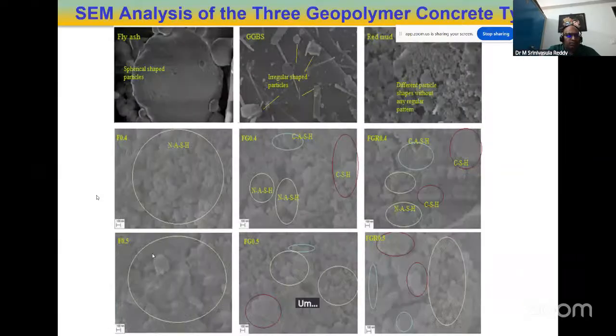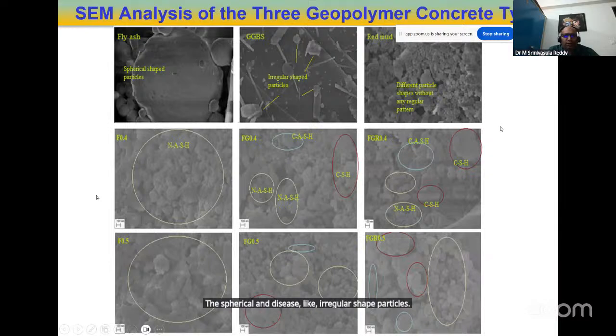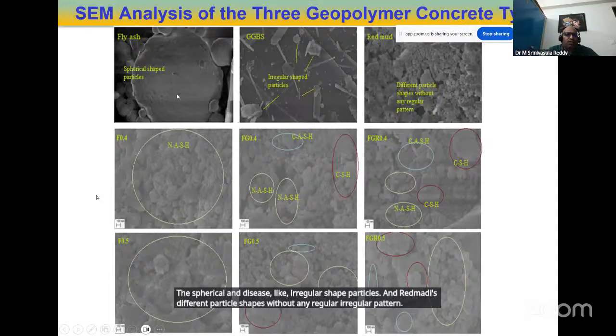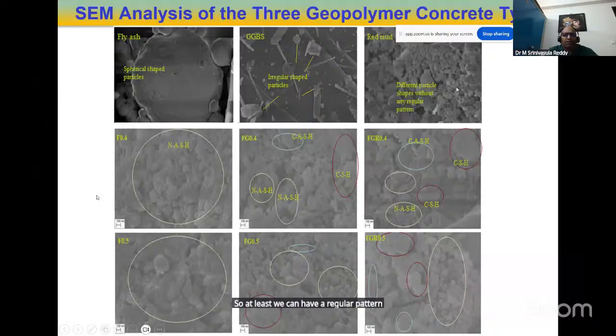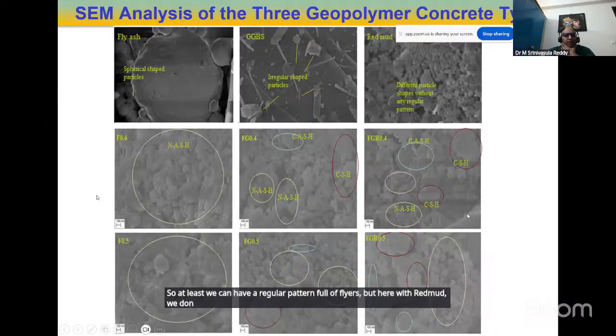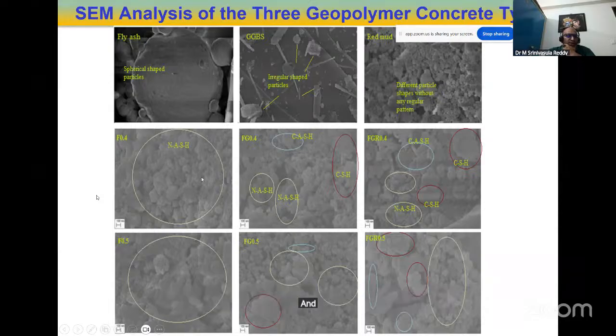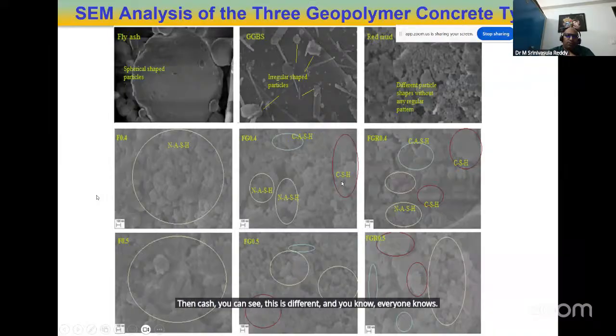And this is the material, the spherical, and this is the irregular shape particles, and red mud has different particle shapes without any regular pattern. So at least we can have a regular pattern for fly ash, but with red mud we don't have any regular pattern. And the main thing, this is the N-A-S-H. You can see this type of structure. Then C-A-S-H, you can see this is different. And everyone knows, whoever knows about normal concrete, how the C-S-H looks like.